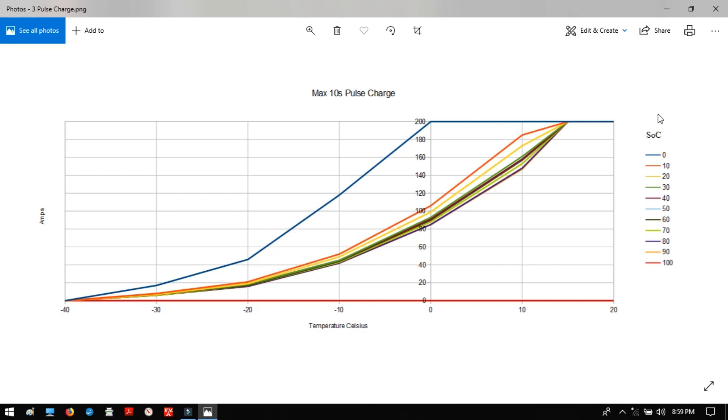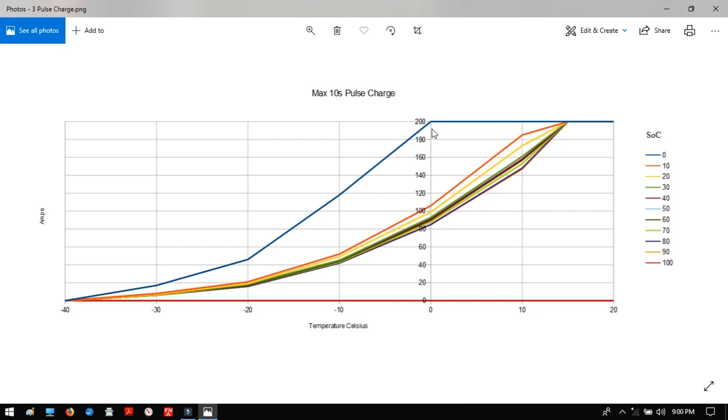Now, as we get into pulses, the variations and differences between state of charge start to come in, creep in a little bit more. And so, of course, again, at 0% state of charge, you can take your biggest 10 second pulse of charge, it has the most capacity. But very quickly, you will go from zero to this first red line of 10% state of charge. It doesn't take long. And so, for instance, at 20 amps, to get from there to there is very fast. So you don't say, well, I can give it 200 amps to pulse charge at zero Celsius, because in just a very few seconds, you're going to be way down here. And the other thing is that this is a 10 second pulse, and then you do nothing for several minutes. And these are all maximums.